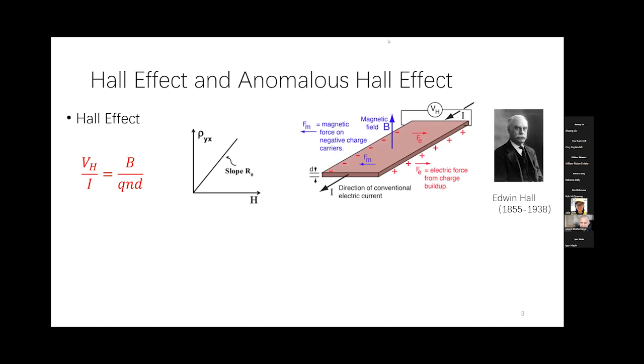Okay, so this slide is about some introduction of the anomalous Hall effect. Before the anomalous Hall effect, you know the ordinary Hall effect, which was discovered by Edwin Hall in 1879. If you apply a magnetic field perpendicular to the current, you will have some charge accumulated on the two sides of the sample, and that gives you an electric field, which cancels the Lorentz force. So we have a Hall resistance, which equals Hall voltage divided by the current, equals B divided by nqd, where q is charge, n is carrier density, d is thickness of sample. So basically, we have a Hall resistance which is linearly dependent on the external magnetic field. Of course, it's a single band model.